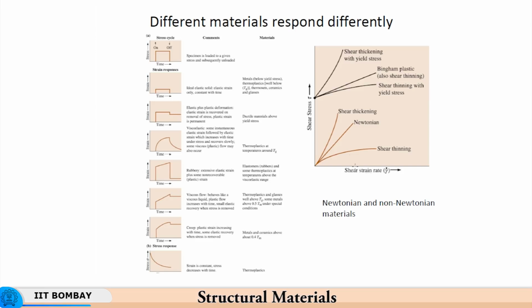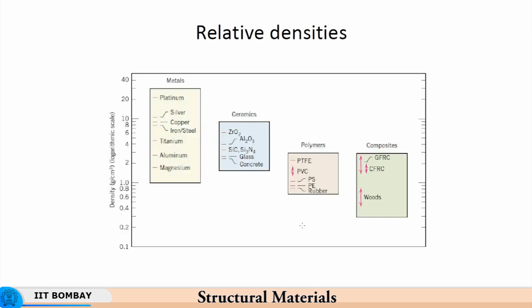As you see, shear stress with strain rate, in Newtonian fluids viscosity is constant, which is also the slope of this curve. Here the viscosity keeps on changing, and finally this becomes horizontal, meaning the viscosity is decreasing. So, slope continues to decrease, indicating shear thinning as a response to increasing shear rate. So, this is what different materials do when you subject them to different kinds of stress. For a given stressing history, the strain history depends upon the kind of material, the temperature that it sees, and so on.